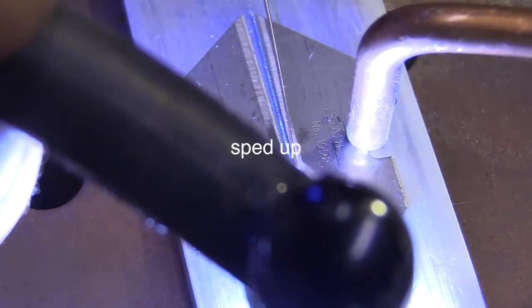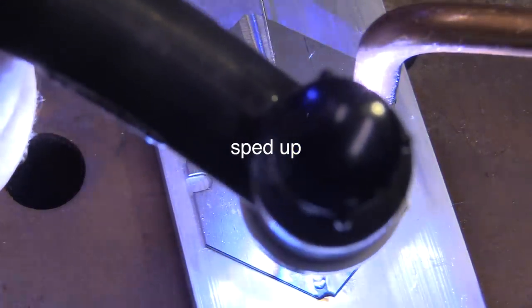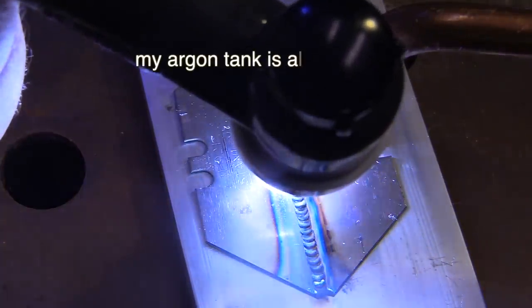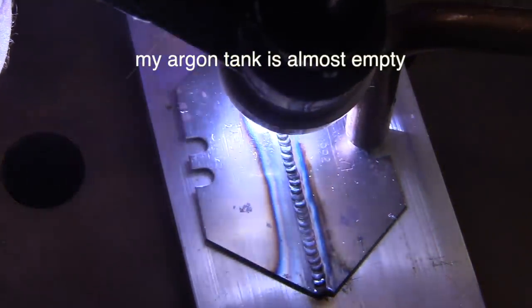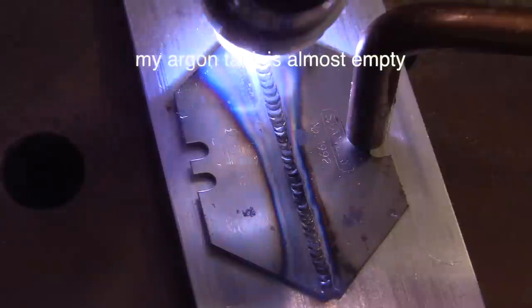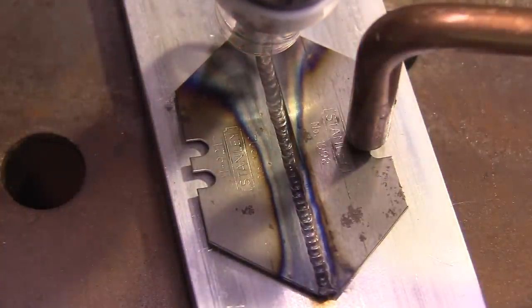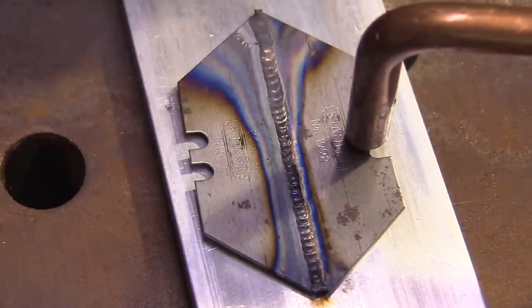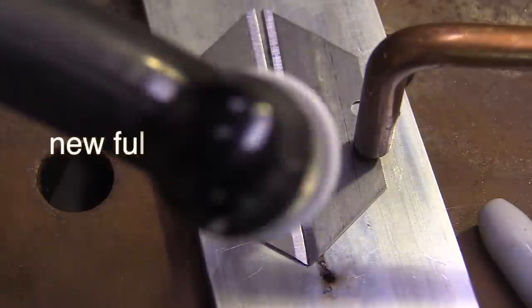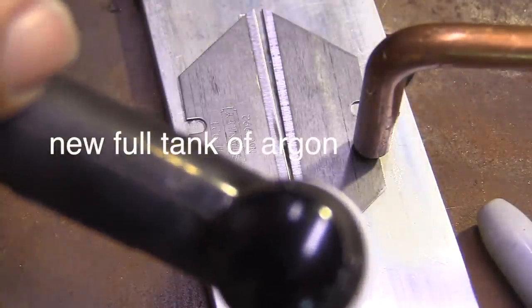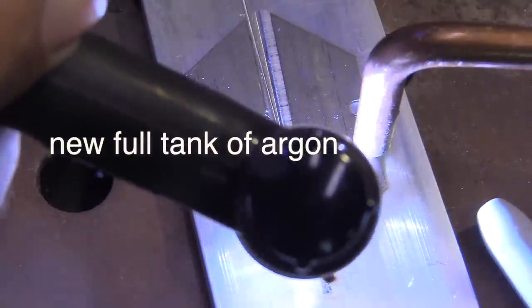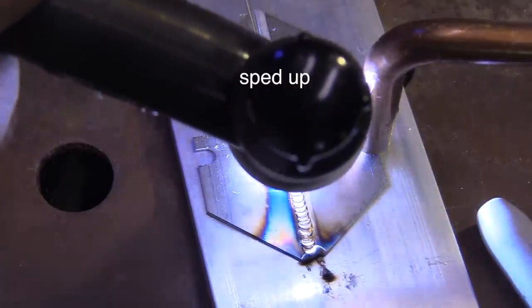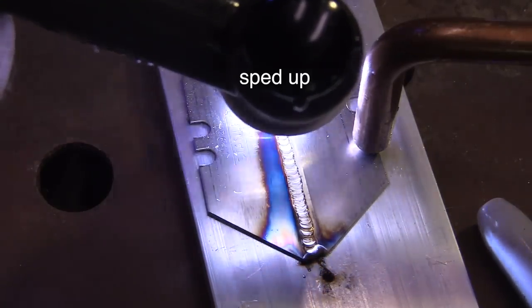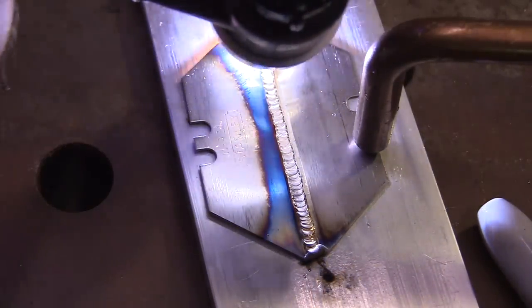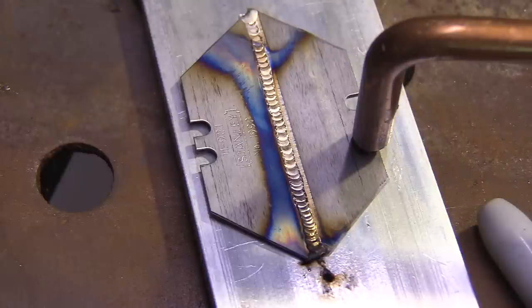I noticed something when I was welding this first set of blades up here, and that was that my argon coverage just wasn't that great. And I looked over and my tank was all the way down to where it wasn't even reading on the flow meter. And so it came out a little gray. Welded okay, started out okay without blowing the corner away, but it just didn't come out nice and shiny. So I switched over to a brand new full tank of argon, and everything went so much better. Didn't change anything, didn't change the flow rate. My flow was good on the flow meter, so it was actually putting out the same number of CFH, but the quality of the gas just wasn't there toward the end of the tank.